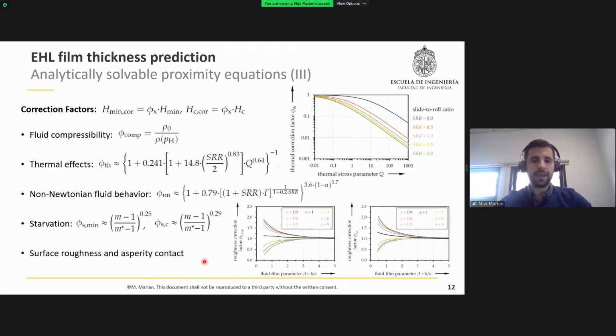development. And when we approach very low film thicknesses, there might also happen some kind of solid asperity contact, which we refer to as mixed lubrication, where basically the load is shared by a hydrodynamic pressure buildup and the solid asperity contact. A first approach to also consider the influence of the surface topography was introduced by Zhu and Cheng, based upon some statistical consideration of surface asperities in terms of microhydrodynamics and load sharing.